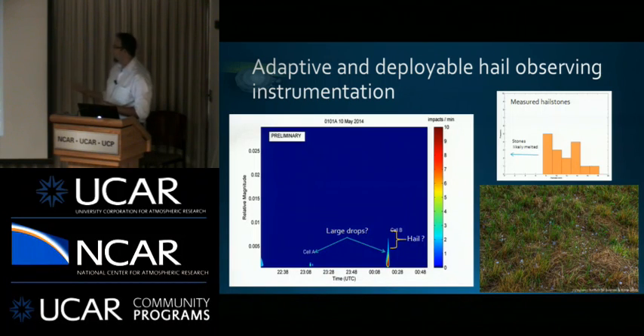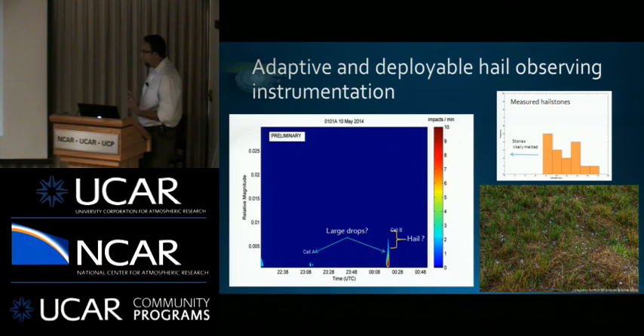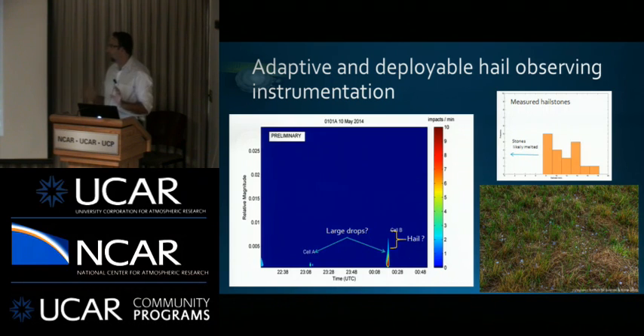The one disadvantage of the Arduino is you have to do a lot of this in post-processing. So you just get essentially a voltage output, and if you try to do any computations within the device processing, it slows down its ability to run at the sampling rate you need it to. And then the next scale, we get a large concentration. So these are essentially impacts per minute, and I have no size algorithm or anything built into this. So we're looking at essentially a relative magnitude, or a percent of full scale of what the thing can handle in terms of a voltage range in our piezo.